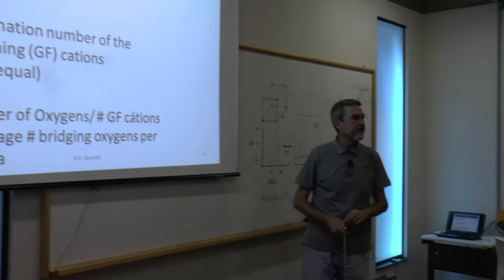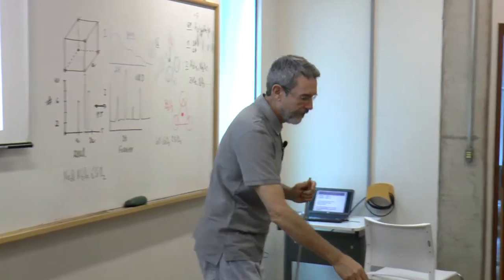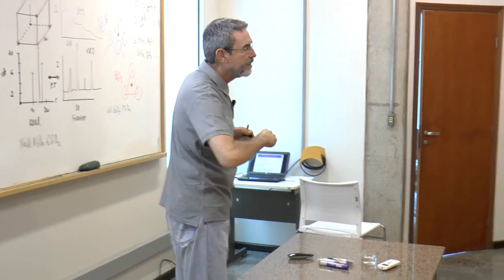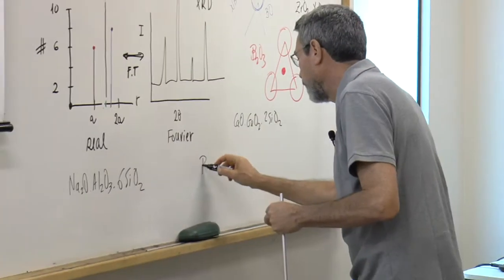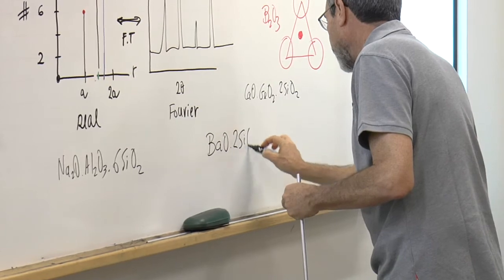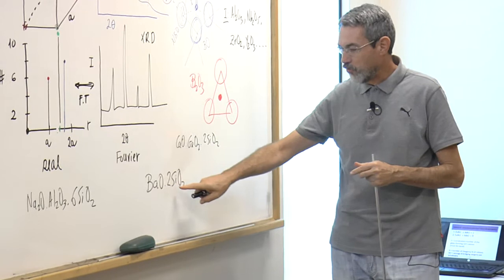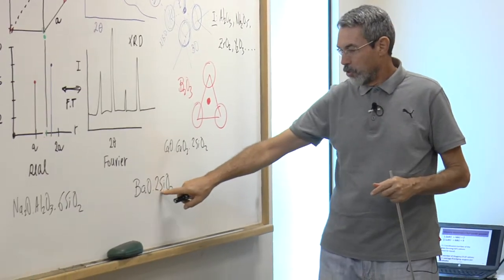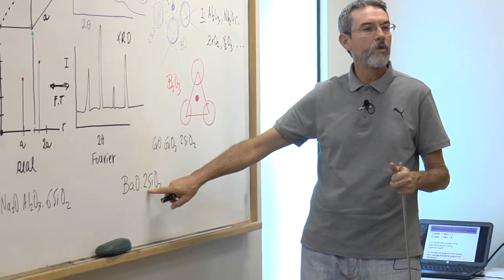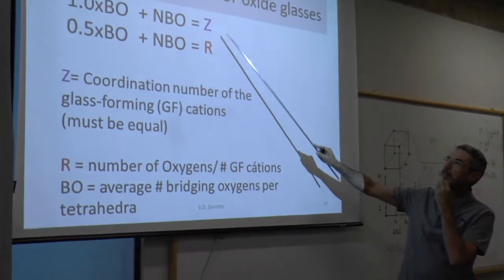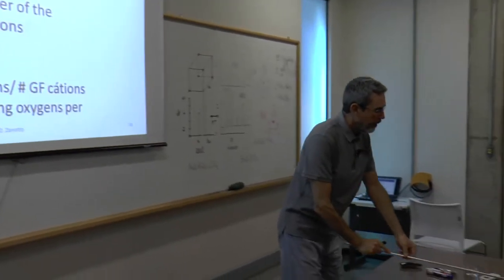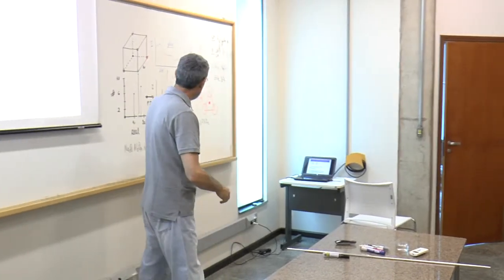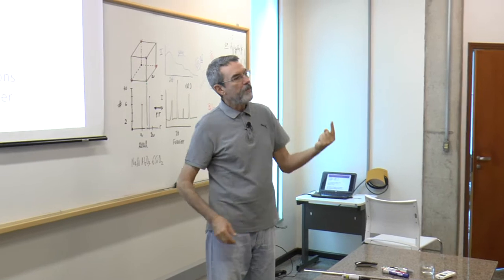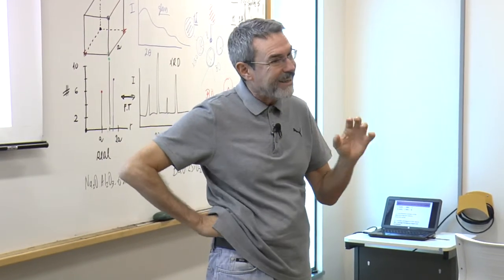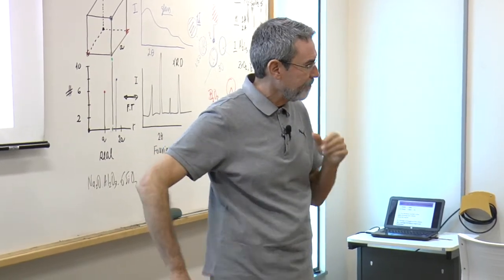Okay, guys? Manuel, is that clear? No. What's the composition of your glass? Barium disilicate, BaO·2SiO2. So Z is 4, and R is 2 times 2, 4, plus 1, 5, divided by 2, 2.5. So R is 2.5, Z is 4, then you can solve the equation. And I know the result for your glass because it's a disilicate, so it will be Q3: 3 bridging oxygens and 1 non-bridging oxygen per tetrahedron, on average.